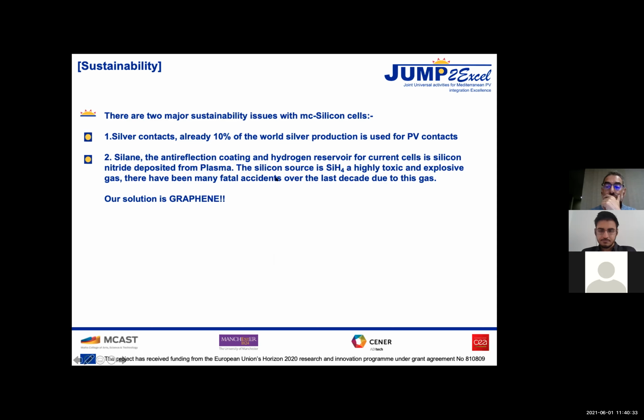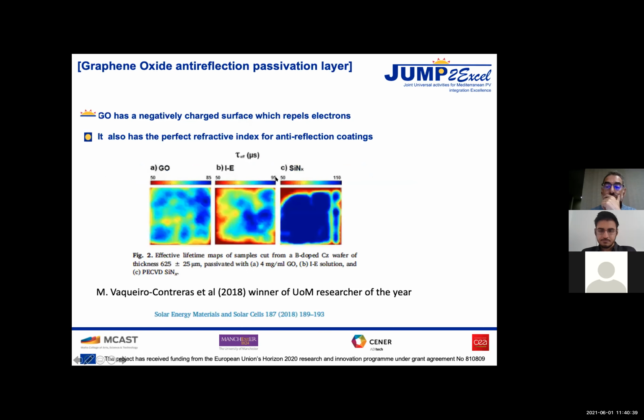So of course, we're Manchester. Our solution is graphene, as always. So we've been looking at graphene oxide. This is something else that Michelle did. Graphene oxide is spun from solution. It's basically a layer of carbon and oxygen on the outside. The outside is negatively charged. It repels electrons, so it's good for keeping electrons away from the surface of silicon, where surface recombination occurs. And it also has the right refractive index. It has a refractive index of 2, and you can just spin it on. You don't need to deposit it from high temperatures from a plasma or using silane or anything. So we can put that on and passivate the surface. So this is passivation. You can see not quite as good as silane, but not bad.